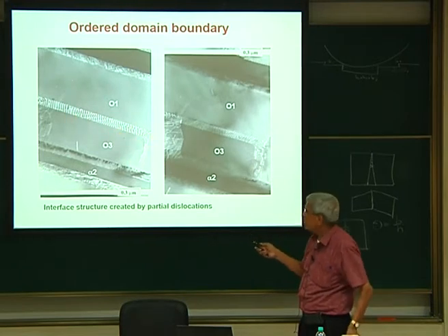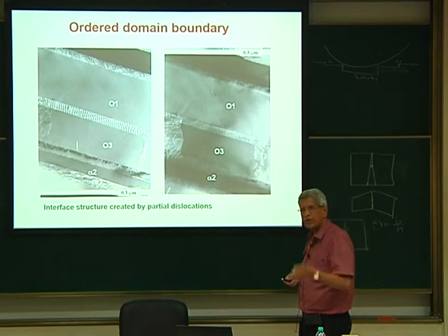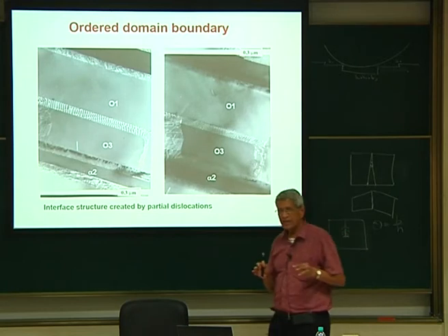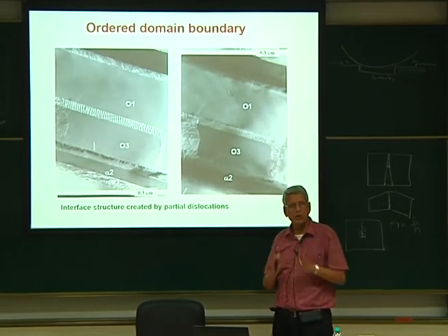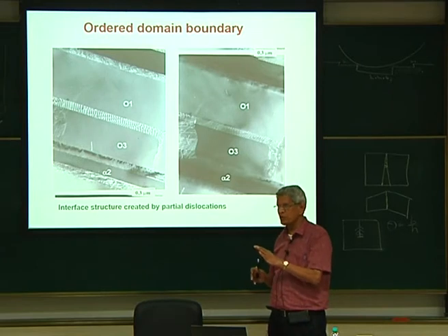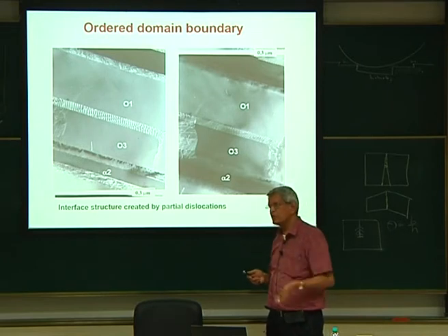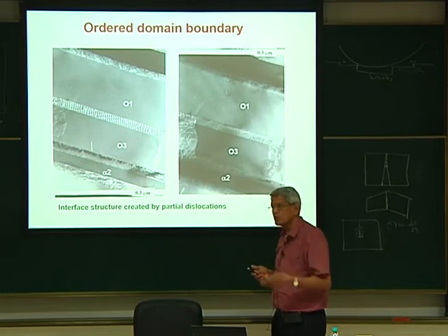So this is another type of boundary, which looks like a plane. This is peculiar to ordered lattices. That is one reason why, compared to a disordered material, when it orders, even within a single crystal you have so many types of interfaces generated. All of them act as obstacles to dislocation motion, in addition to diffusion being slow, and because of that it leads to hardening.